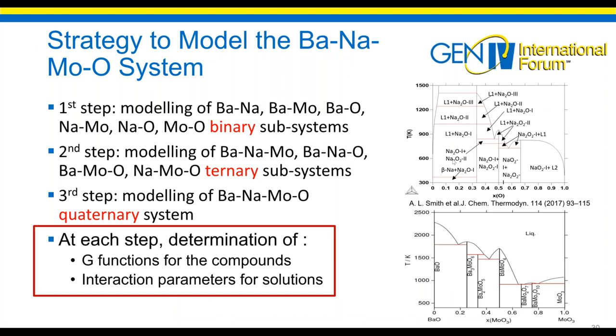So now that I have shown you how to get some input data about the structure, I will explain what I will do in my last year of PhD, on one of the models, the barium, sodium, molybdenum, oxygen system. So to build the CALPHAD model, the first step is to model the binary subsystems. Then, as we showed in the table, this is done. Then the second step is to model the ternary subsystems. So like here, for example, between barium oxide and molybdenum O3.